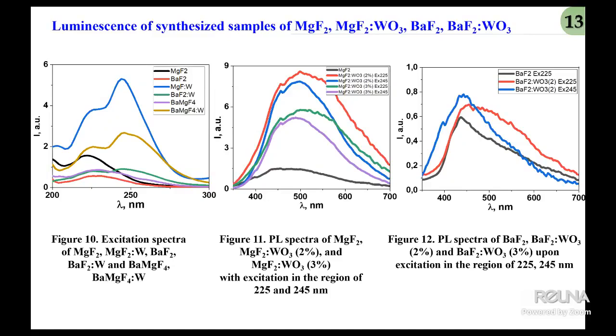This slide shows excitation spectra of the investigated samples for non-activated MgF2, BaF2, and BaMgF4 matrix. A single maximum at approximately 220 nanometers is observed, corresponding to two intrinsic matrix transitions. In the activated MgF2 with tungsten, this is figure 11.